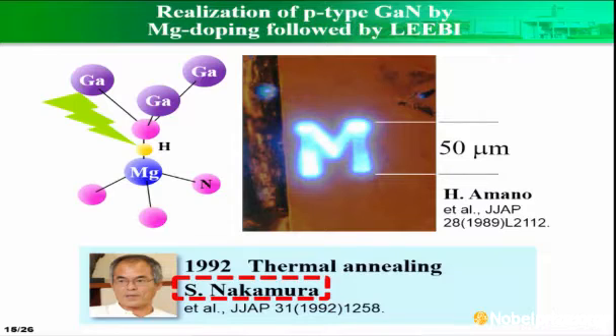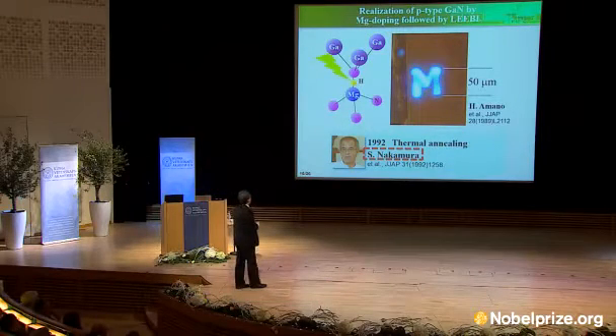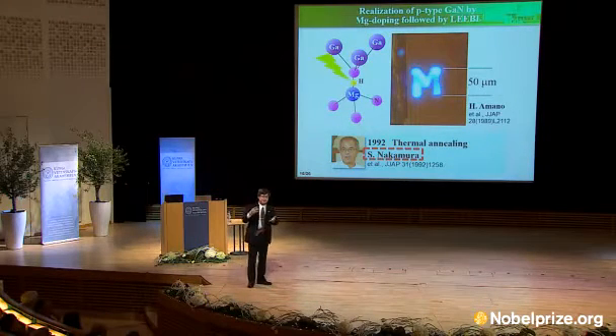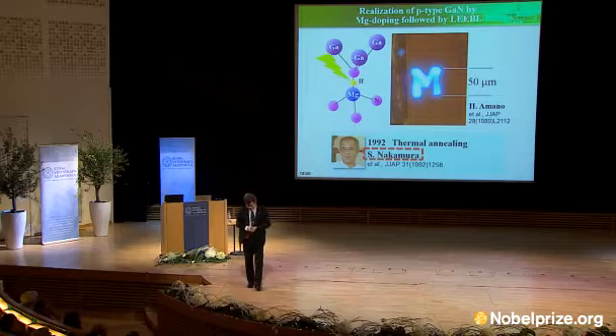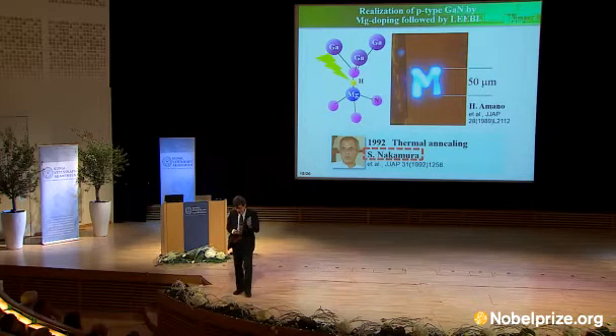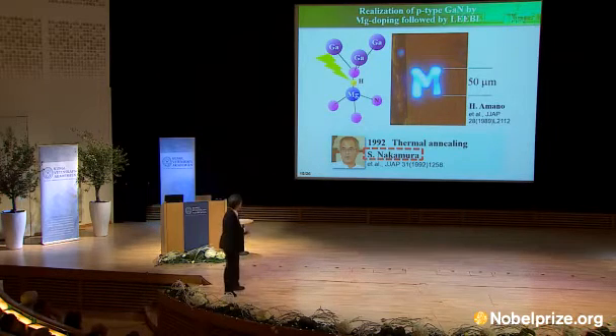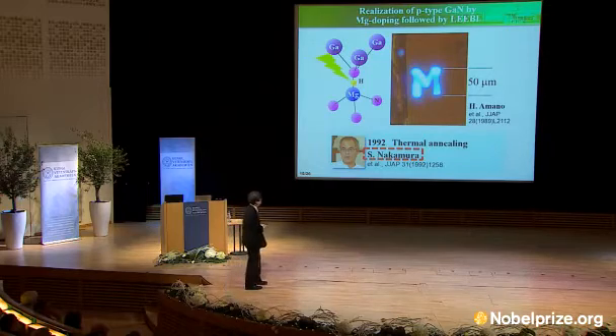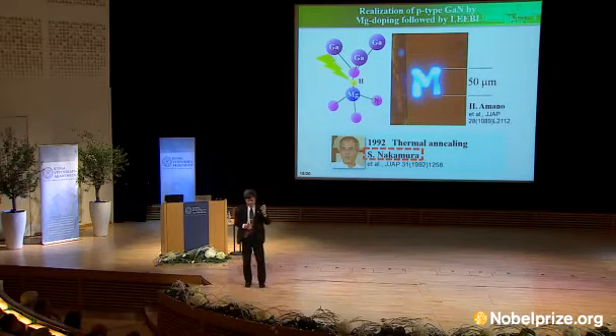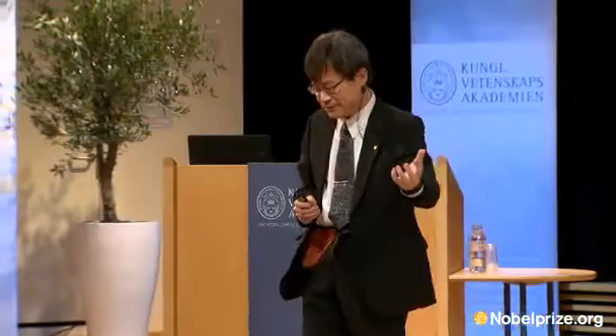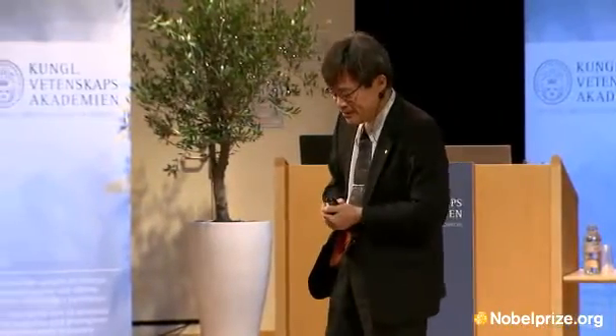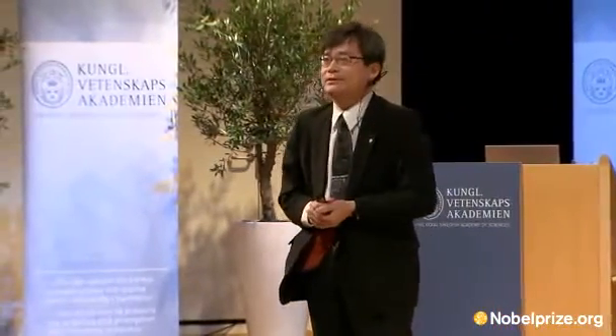Dr. Kito, at that time a master's course student, and I grew plenty of magnesium-doped gallium nitride. The as-grown magnesium-doped gallium nitride was highly resistive, but after the LEEBI treatment, Dr. Kito said that some samples showed p-type behavior.